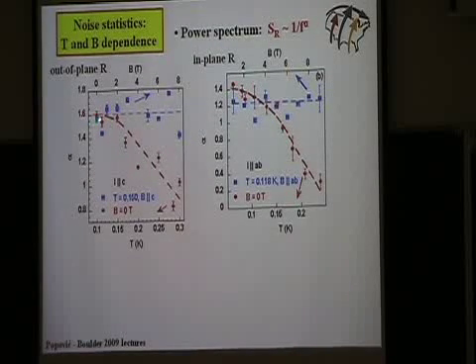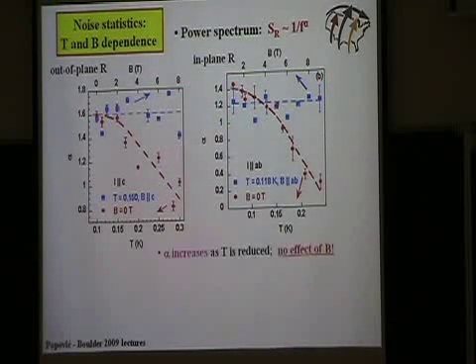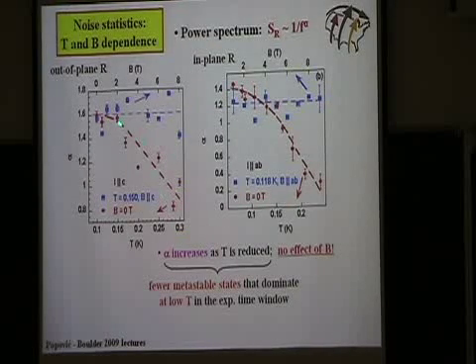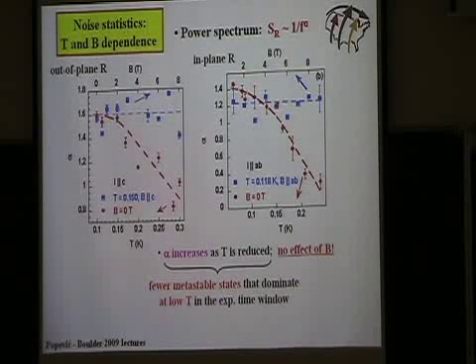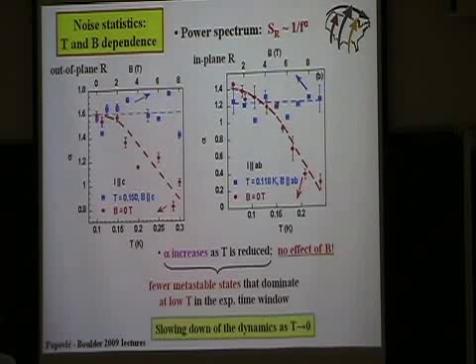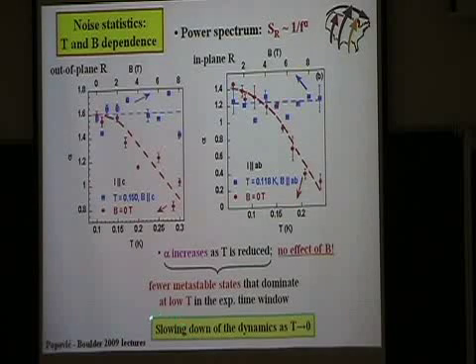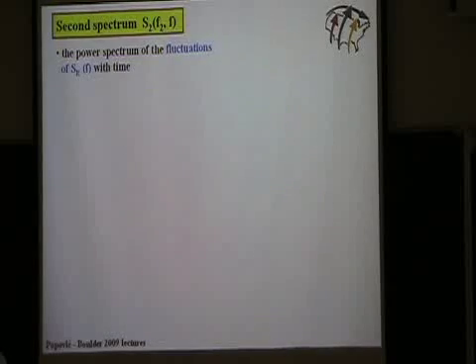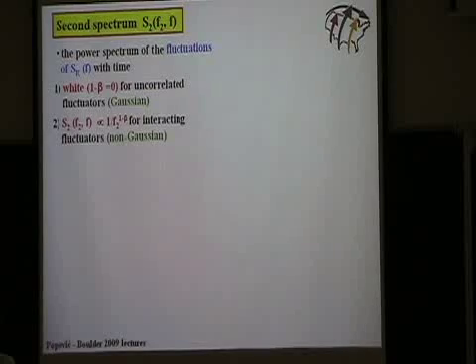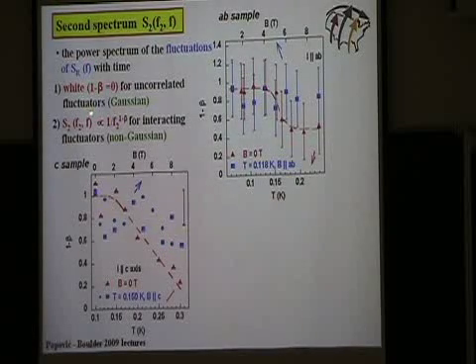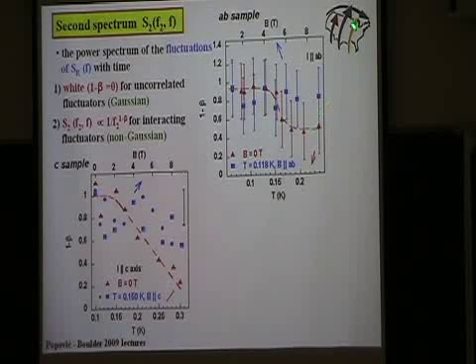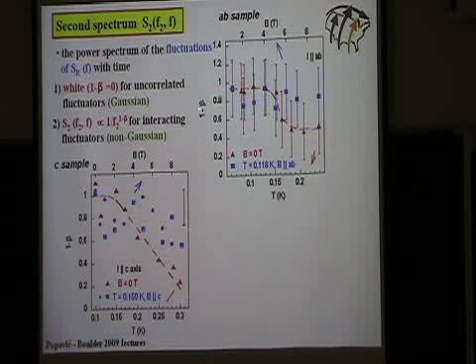On the other hand, the effect of the magnetic field at low temperatures on this alpha, within the error, does not exist. So this means that since alpha grows, fewer and fewer metastable states dominate transport at low temperatures, at least in the experimental time window. So this, just as we saw before, tells us that the dynamics is slowing down gradually as temperature goes to 0. Now you can look at the second spectrum. Okay. So again, 1 over 1 minus beta is the measure of the correlations. This is again transport in the plane, out of the plane. Red points show the temperature dependence. The correlations grow as we reduce the temperature.